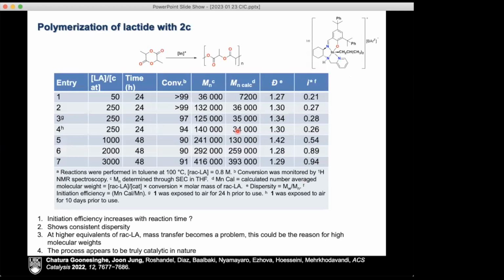And what Chatura was able to show is that these catalyst systems can actually generate very high molecular weight polymer with high initiation efficiencies and low dispersities.